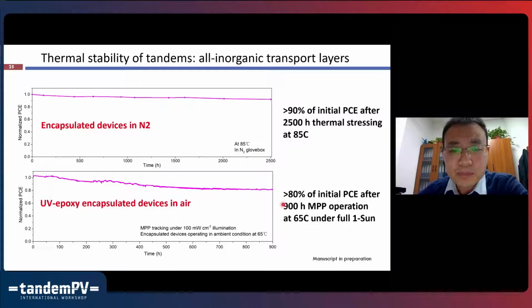And we also tested the operational stability in ambient air at 65 degrees. The device can maintain almost 80% of their initial performance after 900 hours of operation. And this work is under preparation for submission.